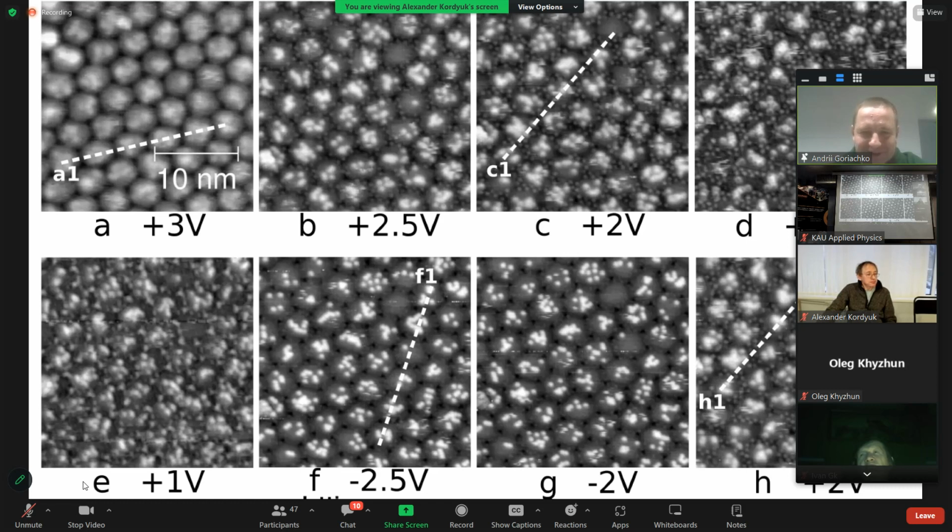So in some situations, for some electron energies, they can tunnel through, or some of them just tunnel into it. And we have been able to tell this difference by being able or not being able to observe the substrate germanium atoms in the STM images of the germanium substrate covered by the graphene layer.